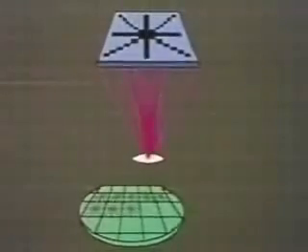The second mask, used to define the actual transistor regions, is also exposed across the surface of the wafer. The wafers are developed to remove the exposed photoresist, then rinsed and baked. The wafers are then plasma etched. The free fluorine atoms react with the exposed nitride. After the photoresist is removed, the wafers go back into the oxidation furnace.